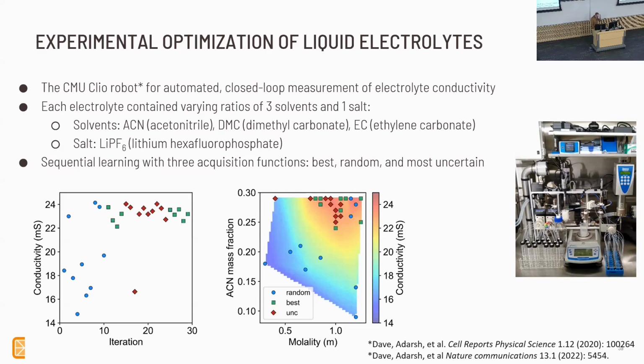So you can see as a function of iteration, we started with just a kind of a random sampling of these formulation compositions just to be able to initialize the data set. Then we turned on our sequential learning to look at two different methods. In this case, we call them best and uncertainty, but those are basically the two methods I showed before, exploration and exploitation. And the idea was now in an automated way, without a human in the loop, we could find out what is the best within this space that we were mapping out here with our underlying model. What is the best composition to use? And then that's what we were comparing against to other materials.